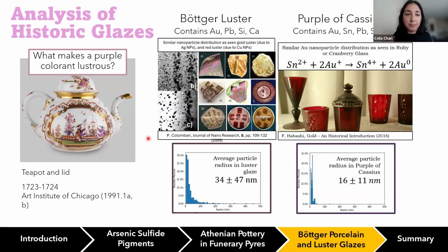Before that, luster was typically, or I guess more common forms of lusterware were made out of silver and copper nanoparticles. So the literature was all based on these studies on silver and copper nanoparticles. Some methods for preparing these luster glazes involved first firing a glaze, adding metal salts directly onto it, firing it again at a slightly lower temperature, just enough for those salts to diffuse into the glaze and then nucleate into nanoparticles. And this is all being fired within reducing environments.